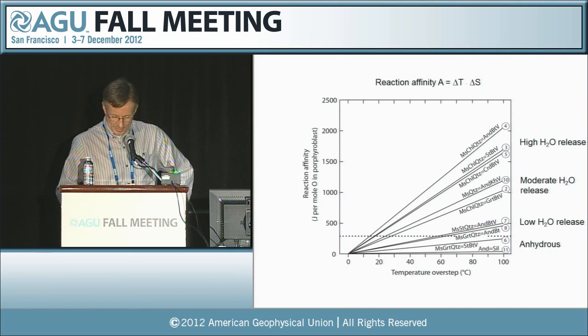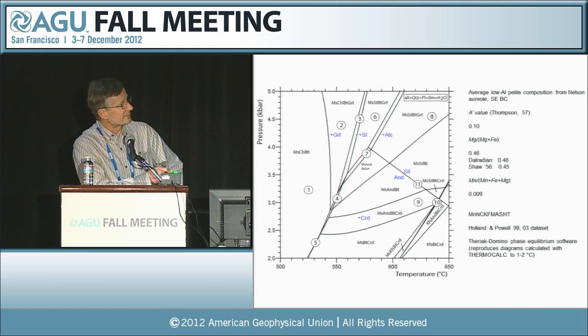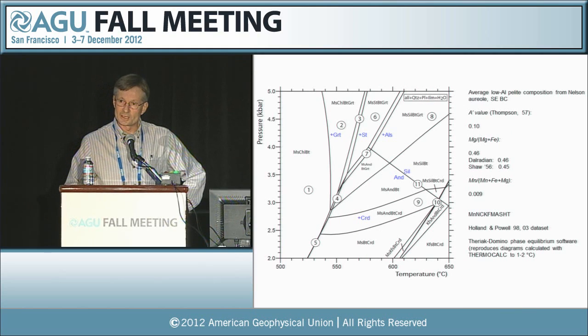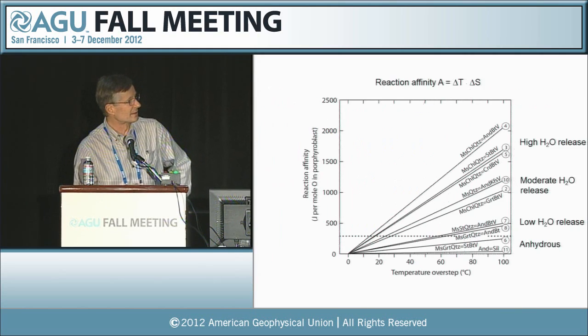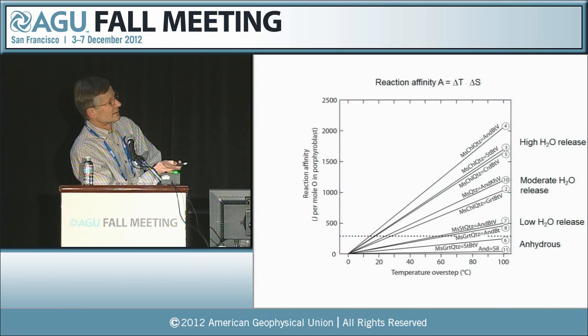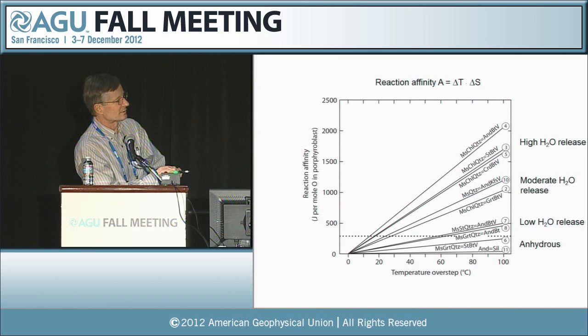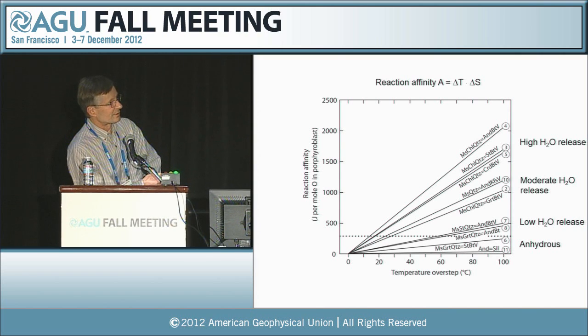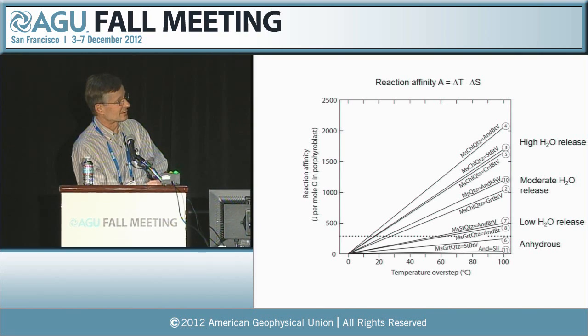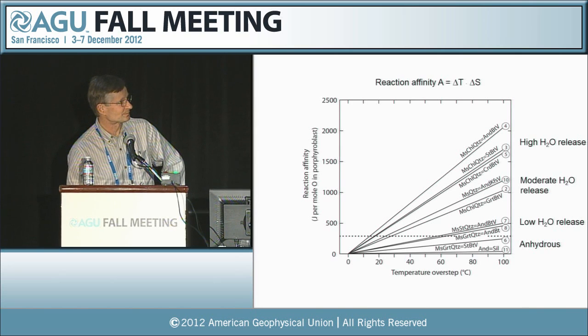If you take the numbered reactions from this previous diagram and actually calculate the rate of buildup of reaction affinity with overstepping, you get this graph here. This is reaction affinity in joules per mole of oxygen in the porphyroblast on the vertical axis, and this is temperature overstep. You can see that there's a big range of slopes here, with the highest entropy reactions having the steepest slope and decreasing down to low entropy reactions, which are at the bottom here. And this broadly correlates with the amount of water that's released in the reactions.